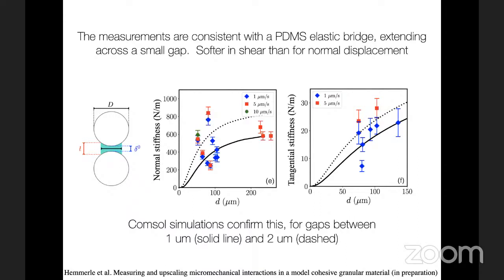There's quite a lot of scatter in the data, but if we try to do the same thing with a COMSOL simulation of the geometry of two round particles connected together with a blob of polymer between them, we find comparable results because we know the stiffness of the polymer, assuming that there is a small gap between the beads of about 1 to 2 microns, and the results are a bit variable depending on how large that gap is. This is consistent with particles that might be slightly rough, for example, or where there's a bit of a wetting surface between the particles.